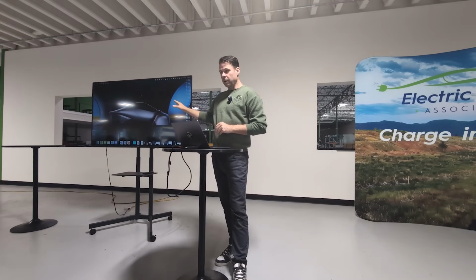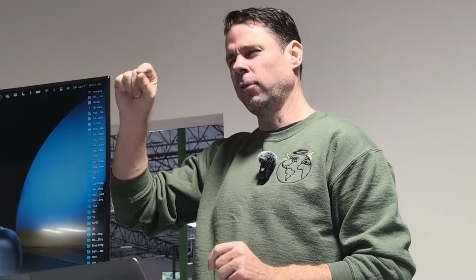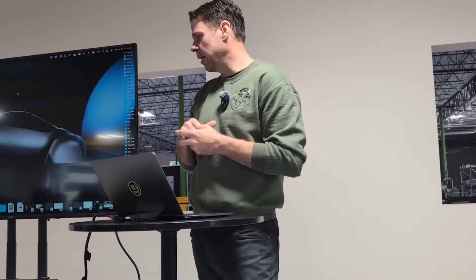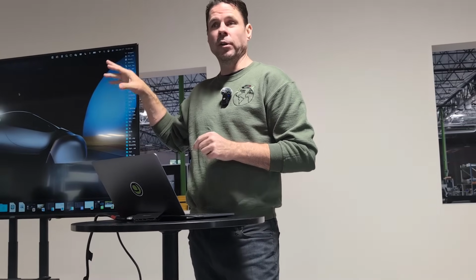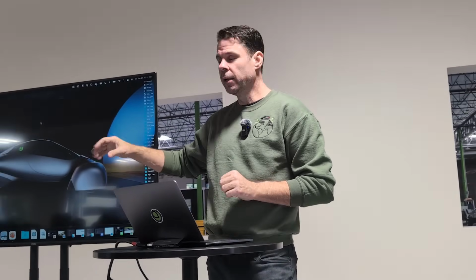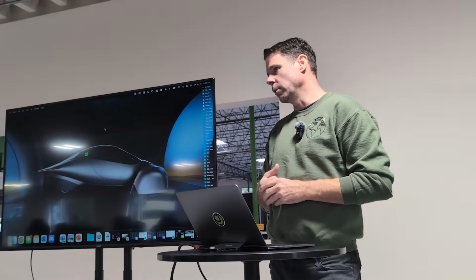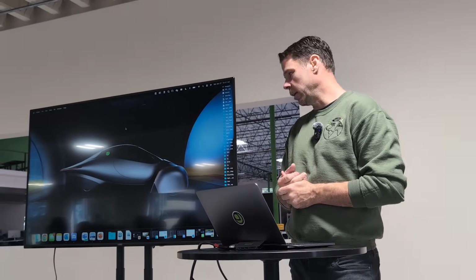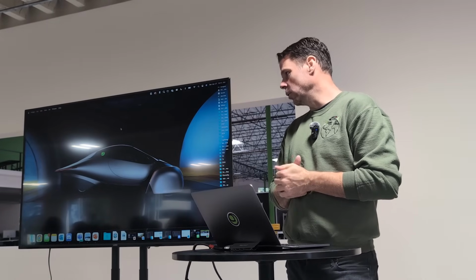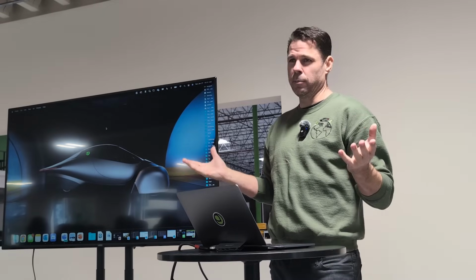The cool thing about the carbon fibers, there's very little waste. There's less than 0.5% of trimmings when you actually produce a part. There's a little flashing that comes out of the side. Like when you injection mold a part, you get a little slag on the side. So they cut that off, and you can actually recycle that material up to 5 times back into a structural part. So from an environmental perspective, it's a quality material. You use almost all of it. There's not a lot of recycle. In steel and aluminum and even the old hand-laid composites, the waste can be up to 30% of your material.